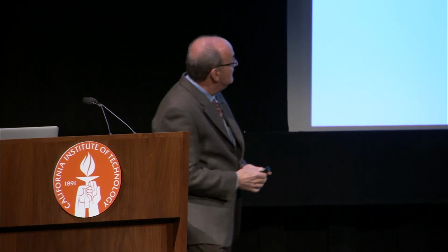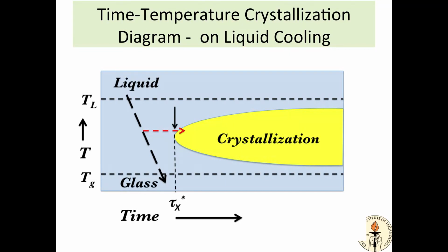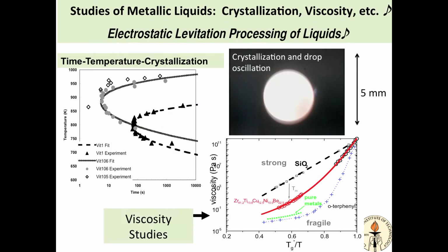Okay? So we study this, and of course, going back here, let me remind you this. So we melt it, we can cool it down and hold it here by adjusting the power of the laser that we're using to heat it. And we can sit here and measure how long it takes to hit this. And so we can measure the crystallization map. And there's the map of Vitreloy 1.